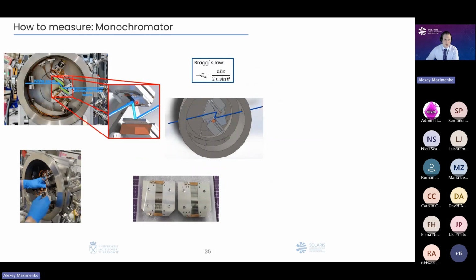So in most of the cases, it is so-called double crystal monochromator, where we have here a wide beam. It means that the beam which is produced by the synchrotron, starting from infrared up to X-rays, coming from the synchrotron. Here we have a crystal, ideal crystal in most of the cases, for example, silicon 111 crystal, and Bragg's law appears here. And this radiation is, let's say, interfere, and this radiation with the proper wavelength, which is defined by Bragg's law, is chosen, and then the second crystal is used in order to return the beam to the same direction where it was going down, where it was incident radiation. That is why we use double crystal structure.